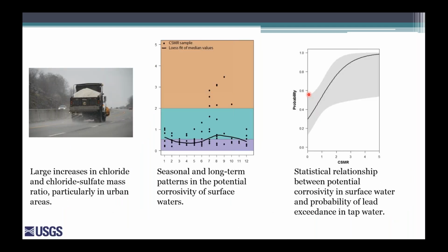Okay, so just to recap the major findings of this study, there were large increases in chloride and chloride to sulfate mass ratio, particularly in urban areas. In addition to the long-term changes in potential corrosivity, there were important seasonal patterns described by the data as well. And I only went over 2 of these, but there are actually quite a few more different kinds of patterns that we observed in the data. And we also found a statistical relationship between the potential corrosivity of surface water and the probability of a lead action level exceedance at the tap.